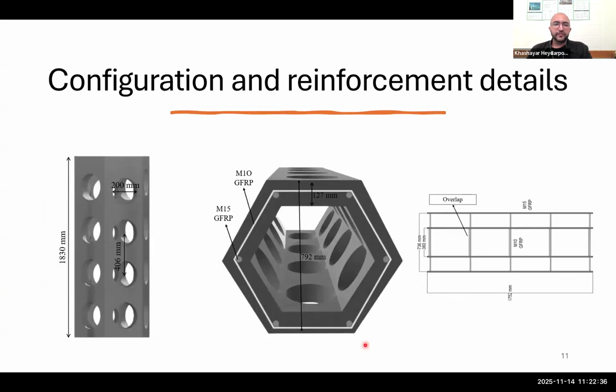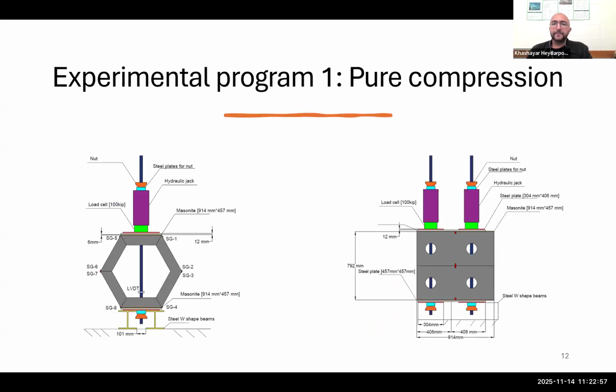And here is also the configuration and reinforcement details of the SEAHIVE. So the longitudinal reinforcement includes 6 number 5 or 15M GFRP bars, along with number 3 or M10 transverse reinforcement. The first 2 specimens were tested under pure compression. The schematic view of the specimens can be observed in the figures, including the configuration and also the placement of strain gauges.